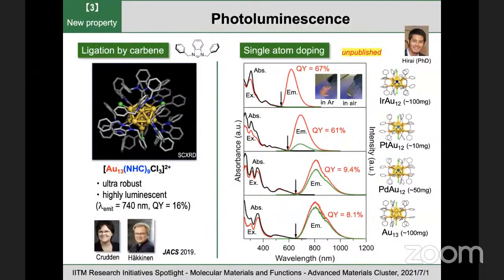The second project we are working on is the exploration of new properties of superatoms. We are interested in the photoluminescence of superatoms. As you can see on the left, gold-13 clusters protected by carbenes are very stable and exhibit photoluminescence with a high quantum yield of 16%.